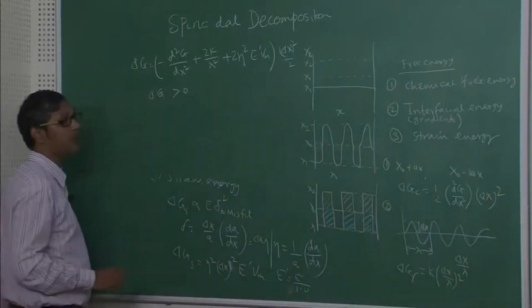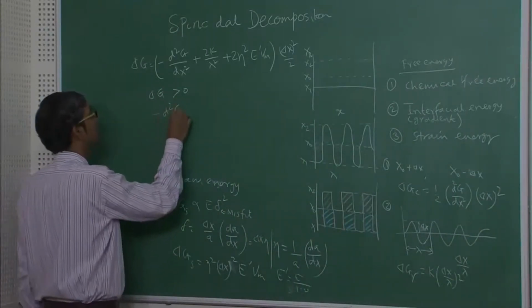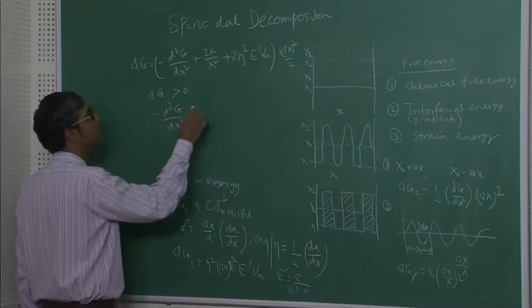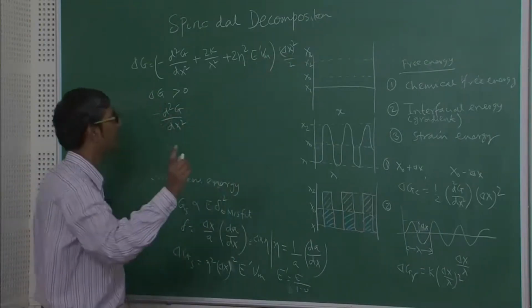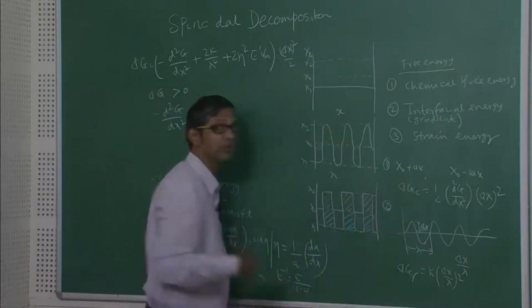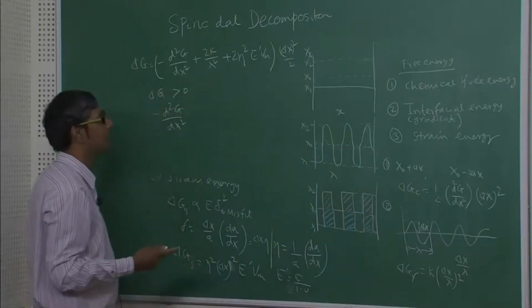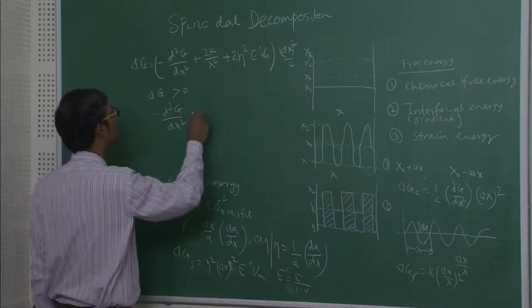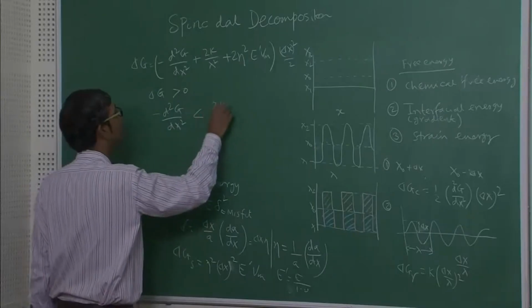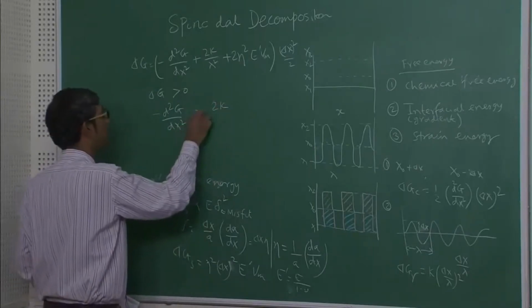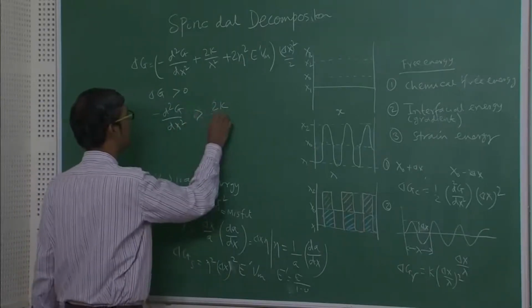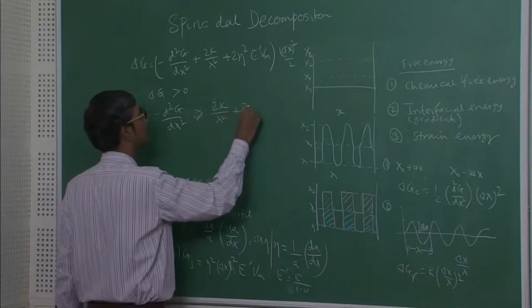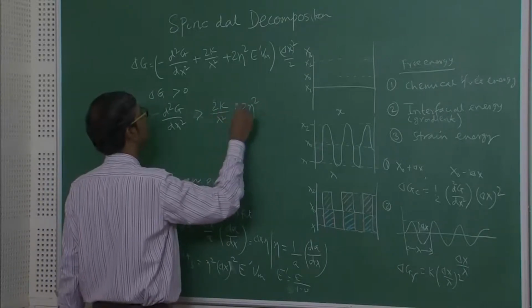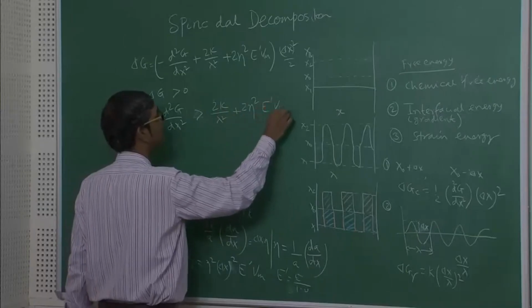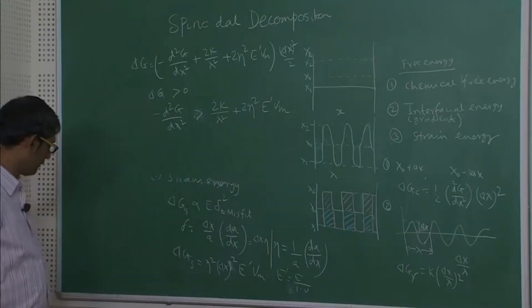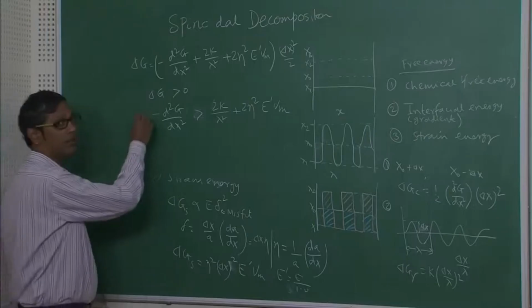That means the solution will decompose very easily into something. So if that is the case, what do I get? I get the condition for decomposition. Obviously delta x can never become 0, right. Delta x is the compositional fluctuation which is growing as a function of time. So this term must be less than or equal to 0. So that is why this will be greater than, the condition for that is 2k over lambda square plus 2 eta square E prime Vm. So that is the condition for decomposition.